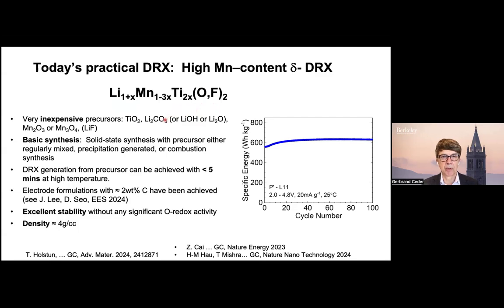This is potentially extremely inexpensive. Manganese precursors and titanium precursors are very cheap. You can use titanium oxide. You can use various forms of manganese oxides. You can even use manganese carbonate if you want to. And the lithium source that we typically use is lithium carbonate, though, of course, you could use the hydroxide, even the lithium oxide if you really wanted to.